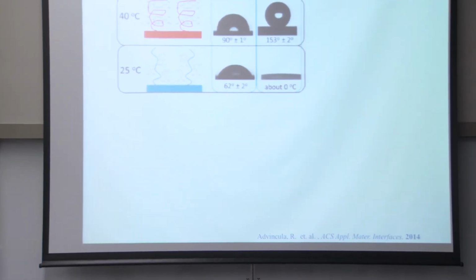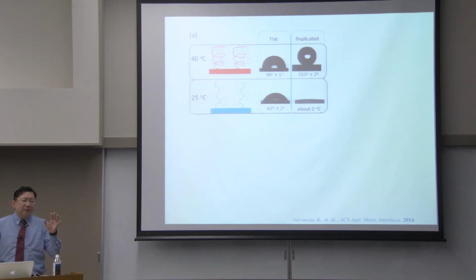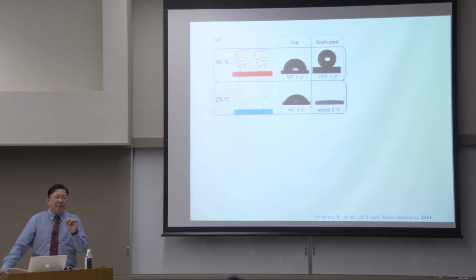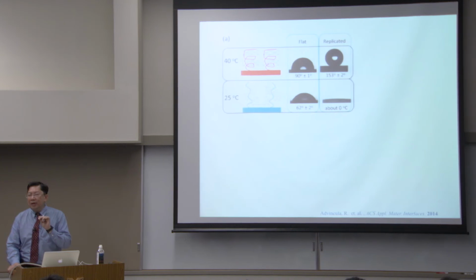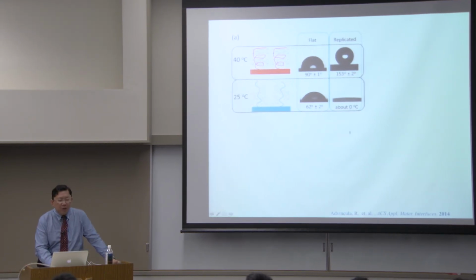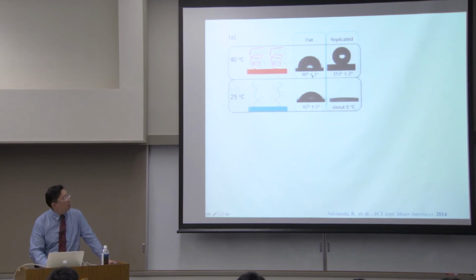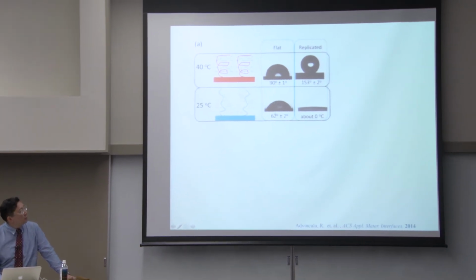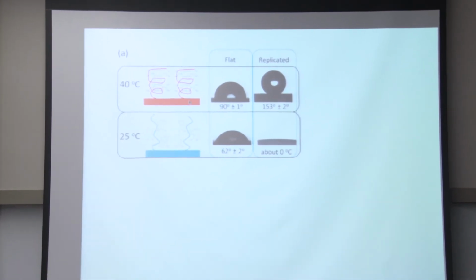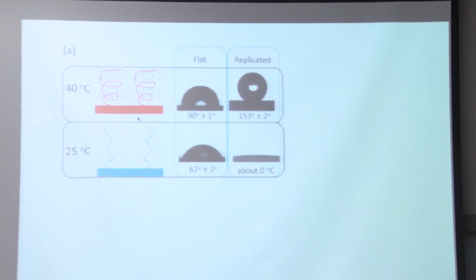Now, what's interesting about this fake lotus leaf? Based on temperature, we can make it wetting or non-wetting. PolyNIPAM is a polymer with what we call a lower critical solution temperature. Here's a surface that was not modified, and you can see it shows a good change in wetting behavior from 62 to 90 degrees simply based on the polyNIPAM action alone.